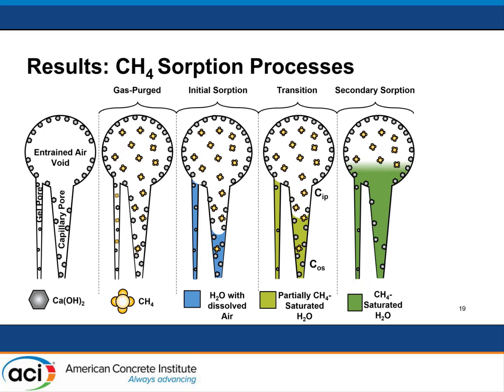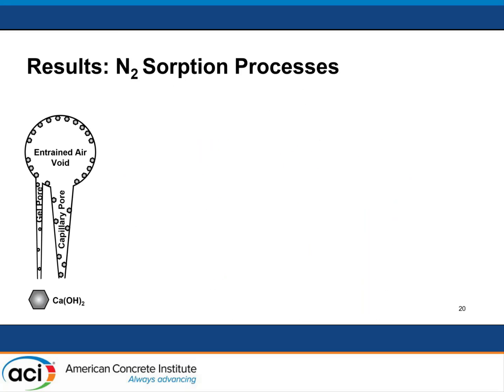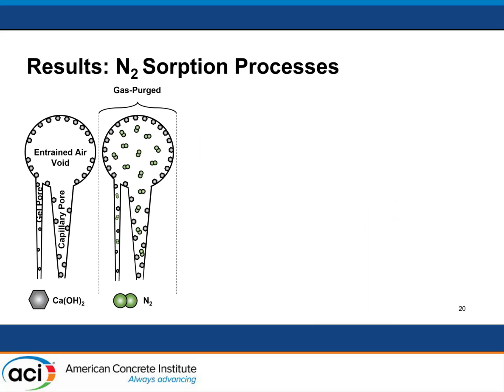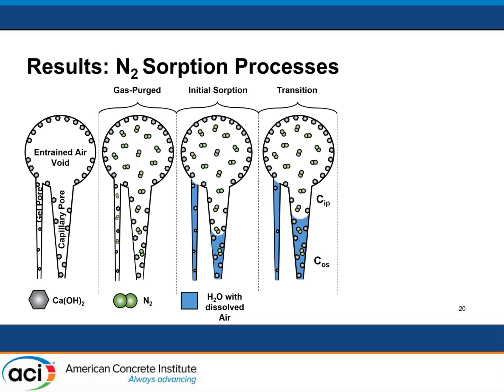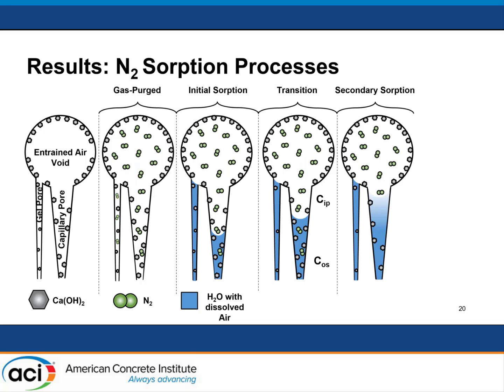filled sample. And lastly, the nitrogen filled system. So we purged with nitrogen. It's already filled with air, and air is nearly 80% nitrogen. So what we believe was happening here is that the water advancing into the system, because it was already pre-saturated, mostly to the point that the remaining nitrogen filling those voids could not dissolve into the water, and that's why it was such a slower process relative to the methane filled sample, even though the solubility limit is very